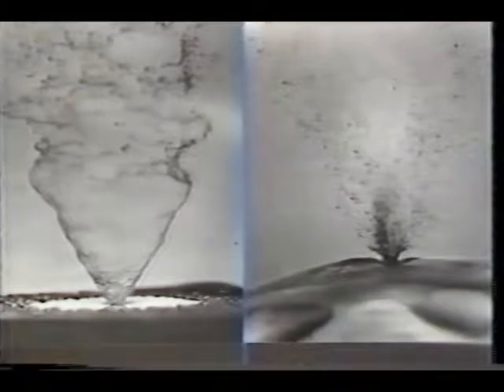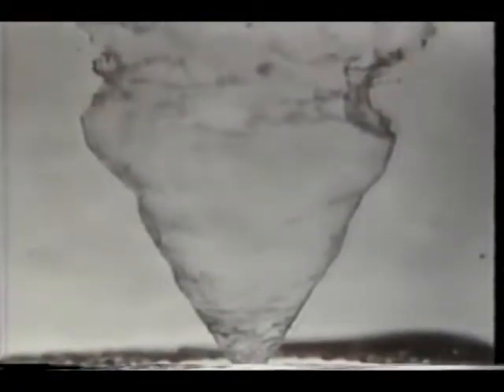Compare the spray from a conventional high-pressure swirl nozzle on the left with the Babington atomizer on the right. Coarse spray particles from the standard nozzle are seen in the upper portion. Note that first a tulip-shaped sheet of liquid is created, followed by a distinct ligament phase, before breaking into various size droplets. The Babington plume of the same magnification shows no ligament phase and much smaller uniform droplets, formed directly from the thin film of liquid flowing over the exterior surface.